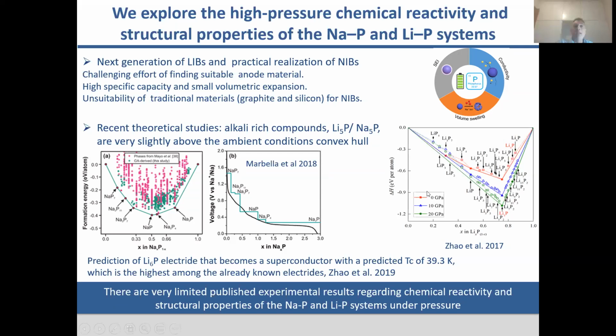This is under pressure for the lithium phosphorus system, predicting that lithium-rich compositions like lithium-5 phosphorus are stable at 10 GPa, and this is the case for sodium. I don't know how clear it is, but sodium-5 phosphorus, at ambient conditions, is just above the convex hull at ambient conditions.